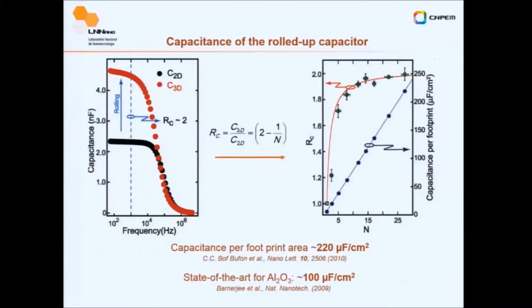So for the electrical characterization, you can see here we simply measure the capacitance as a function of the frequency before and after rolling. You can see before rolling and after rolling, you have a small frequency dependence, probably because of interface states in the mechanically made junction, but you can go roughly twice. And then you see when you increase the number of windings, your capacitance increases, to a ratio of 2. Yeah, and the capacitor footprint reaches about 250.